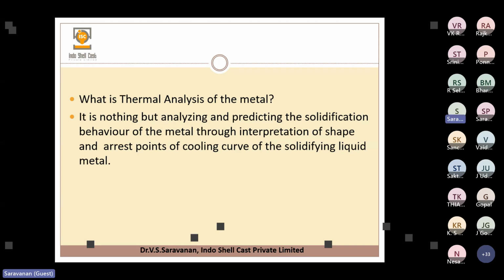So the important thing is how to control the graphite precipitation, how to control the nucleation potential of the metal. All those things are very important as far as cast iron is concerned. Here cast iron means both ductile iron and gray iron, and ductile iron is more sensitive compared to gray iron, because gray iron has a long freezing zone, so it forms a thicker skin immediately. So the pressure exerted on the mold is a little bit less, even though the pressure developed is almost the same, because the thicker skin absorbs some of the pressure. So the bulging-related issue is less, and the shrinkage-related issue is less.